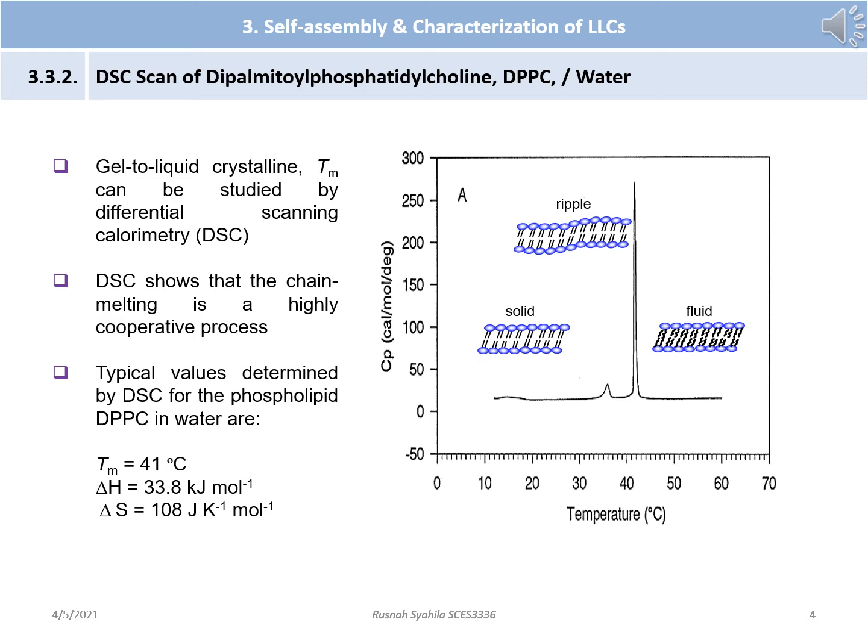The first transition, with small enthalpy change, occurs at 36 degrees Celsius and is the transition of solid DPPC to ripple bilayers. This kind of transition doesn't require much energy. The second transition belongs to the gel to liquid crystalline transition. Larger energy is required for this transition, for melting the chain to make it a fluid bilayer, which is the lamellar phase.